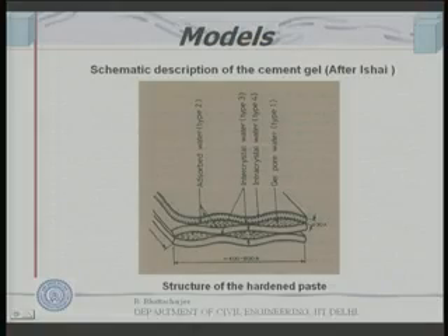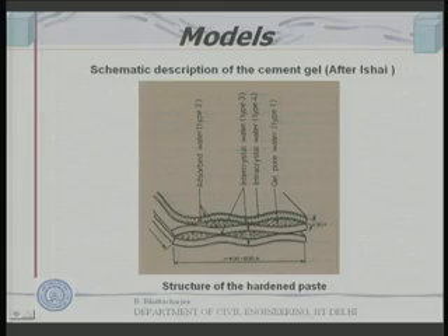One of the models proposed, by Ishai, is something like this. He feels there is a layer structure, and between the layers there is some space where you will have what he calls gel water, because it has a gelatinous structure. So, gel pores exist between the layers. Then there is intercrystal water, there are different types, and also adsorbed water at the layer surface, and this water does not have a density equal to 1; it has a different density. So, you have gel water, adsorbed water or intercrystal water, that is what Ishai's model gave.